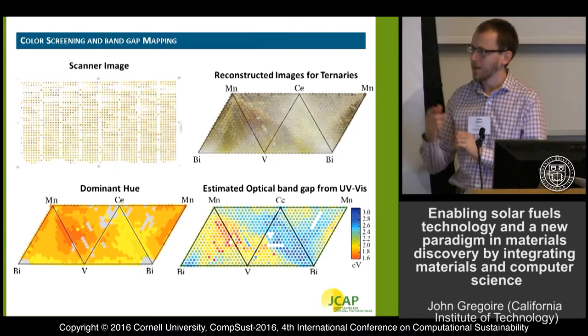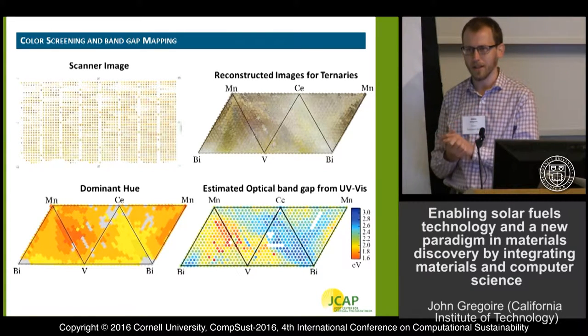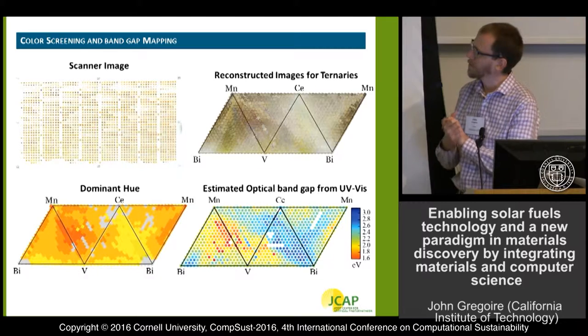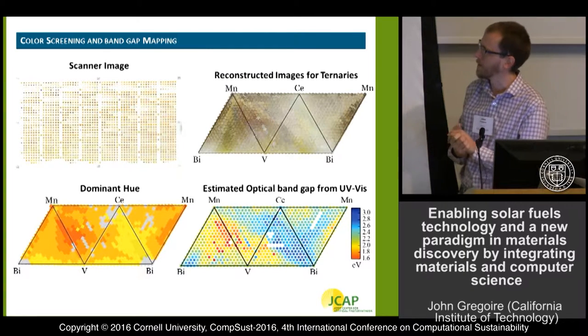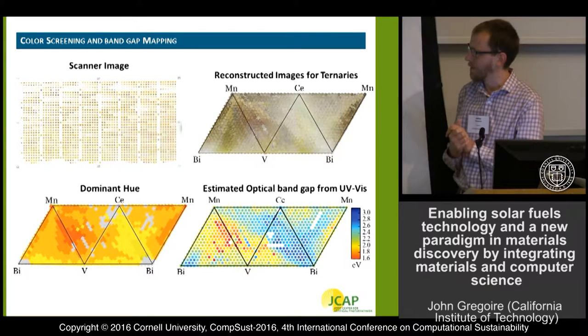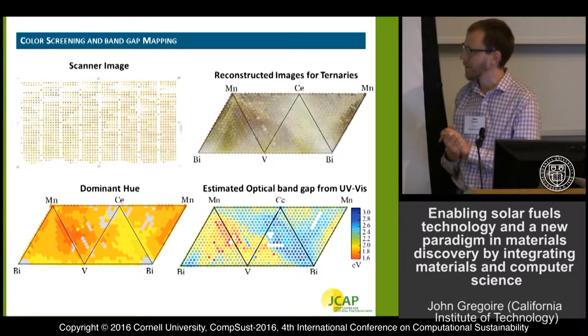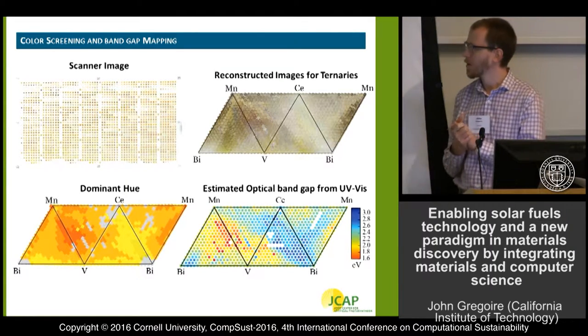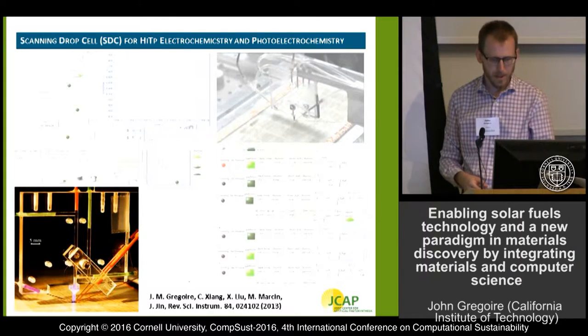Just to give a sense of what these things look like — there's a photograph of one plate with one-millimeter squares. There are 1836 compositions on that plate; about 10 of them had ever been synthesized in a lab before, so there are roughly 1800 new ones. If you take these little images and reconstruct them into composition spaces — the series of triangles I mentioned — you see the visual appearance changes systematically. We can turn that into a representative hue and quantify it more precisely using optical spectroscopy to get a band gap, which is a really critical parameter for solar applications: it determines the range of the solar spectrum absorbable by the material.